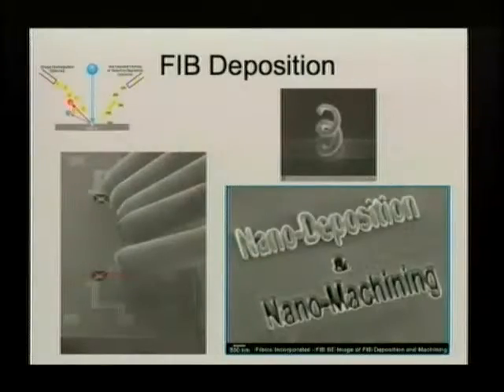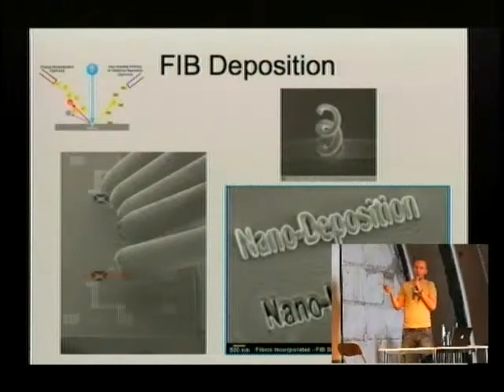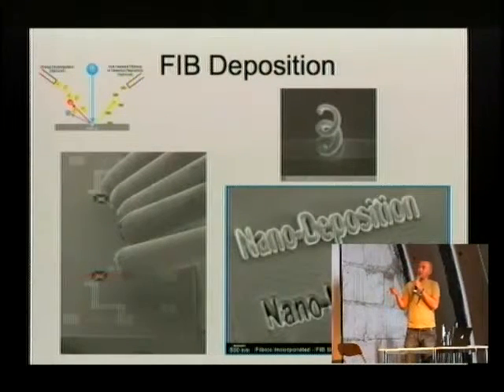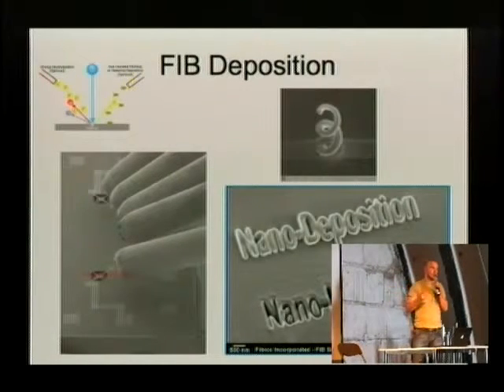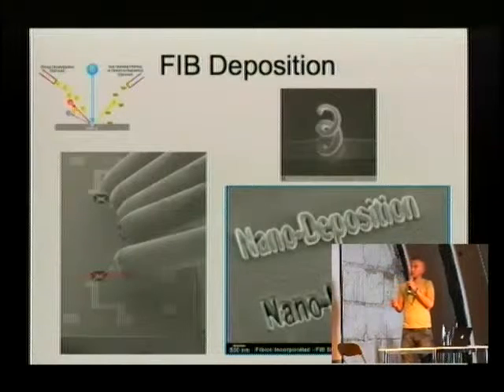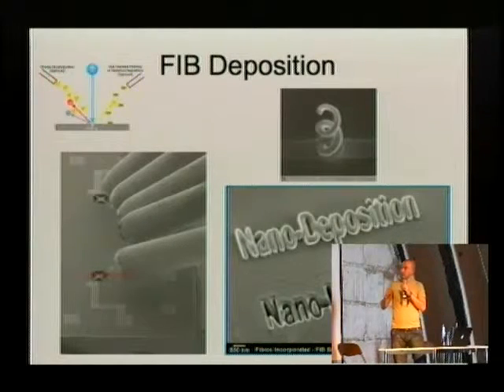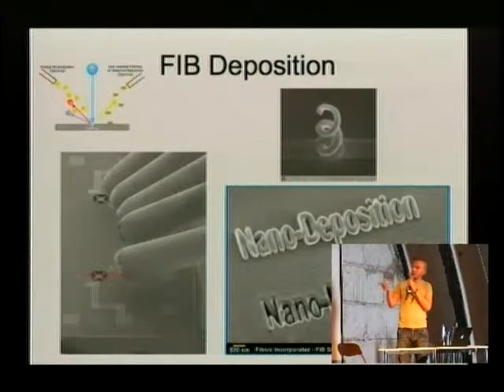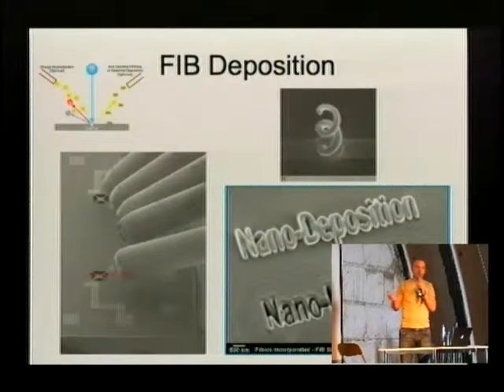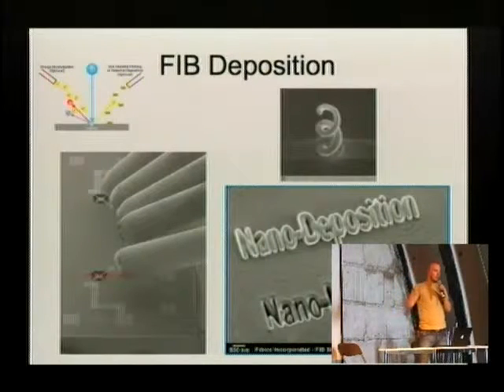There's another thing we can do with the FIB, and that makes it even more interesting than the milling. If we inject some gas into the chamber with a small needle, normally some sort of carbon compounds that bind to a metal or an insulator, you can deposit the material onto the surface. The chemical bonds inside these carbon compounds get broken up by the ion beam, and you can locally deposit